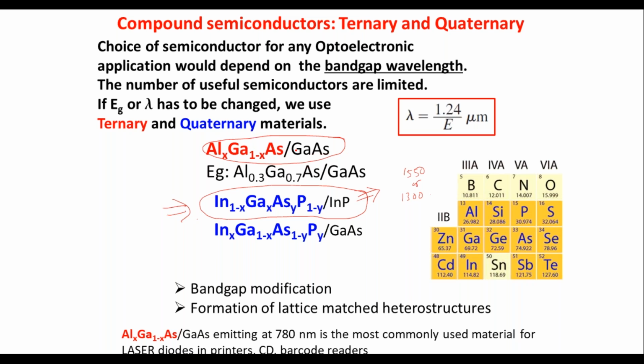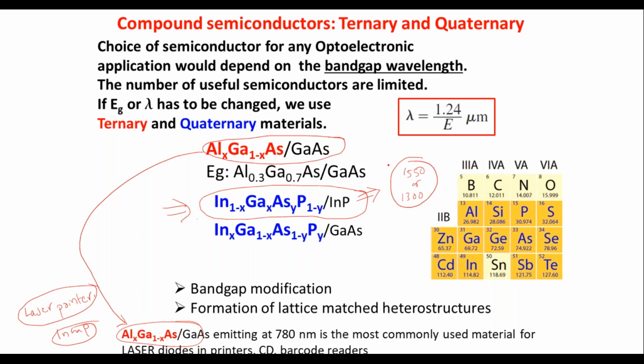The aluminum gallium arsenide and gallium arsenide combination is used in constructing laser diodes. For example, if you have a red laser pointer, those red laser pointers are made out of this particular material. Either aluminum gallium arsenide or it could be indium gallium phosphide. This material is also used. Anyway, ternary materials are used for constructing these lasers, whereas for optical communication, we generally prefer this particular material simply for the fact that it can support this 1550 or 1300 nanometer.